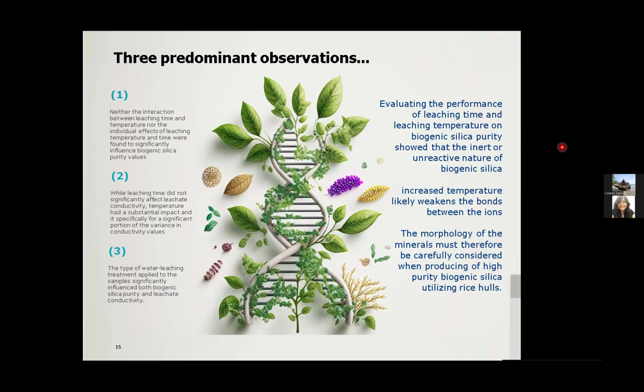And three, the type of water leaching treatment applied to the samples significantly influenced both biogenic silica purity and leachate conductivity. So what does it all mean? First of all, evaluating the performance of leaching time and leaching temperature on biogenic silica purity showed the inert and unreactive nature of biogenic silica. And also, increased temperature likely weakens the bonds between the ions. And lastly, the morphology of the minerals must therefore be carefully considered when producing high purity biogenic silica utilizing rice hull.